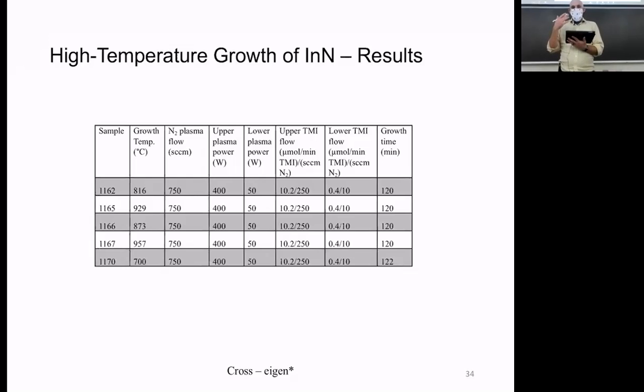The reason that it has been such a big problem is because every time they grow indium nitride, they always have hydrogen in the system, and hydrogen and indium nitride do not react well together. I don't know the exact reason behind that, but every study that comes out says if you have hydrogen, you get bad indium nitride. Back in, I want to say, the early 90s, they used a plasma source again to create indium nitride, and they documented that they could do it at 650 degrees, and then the project may have gotten abandoned or something, and that was the last we ever heard of that result. So throughout my literature review, there was no information about indium nitride grown above 650 degrees that was successful. And that was very exciting because that means I got to publish a paper. And that paper became part of my dissertation.